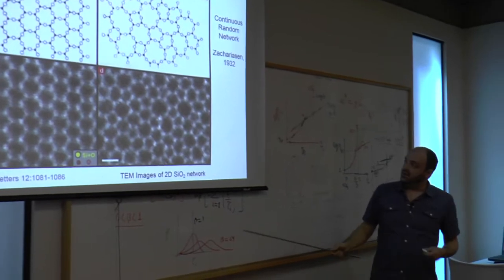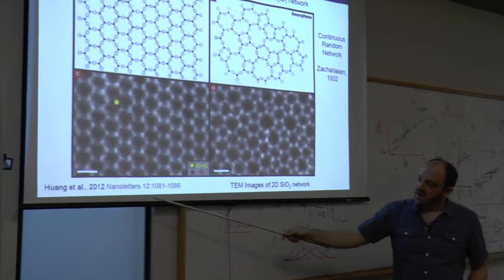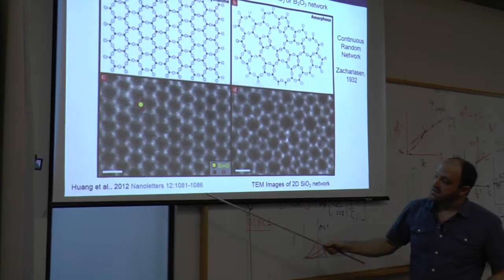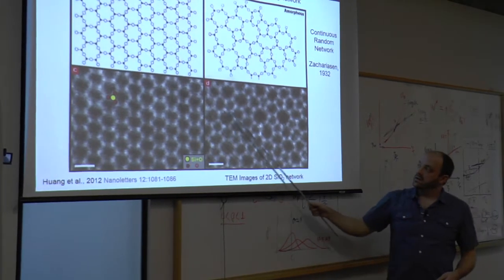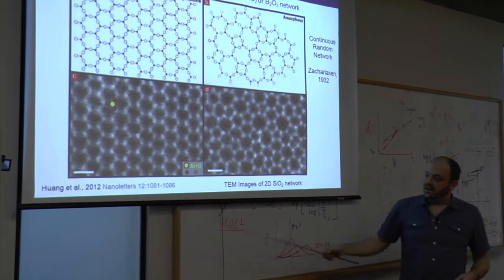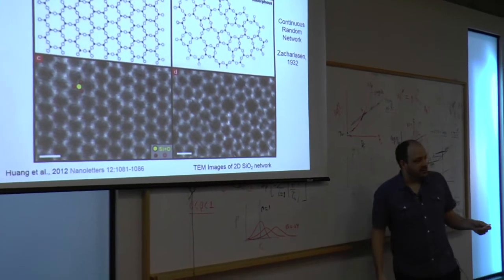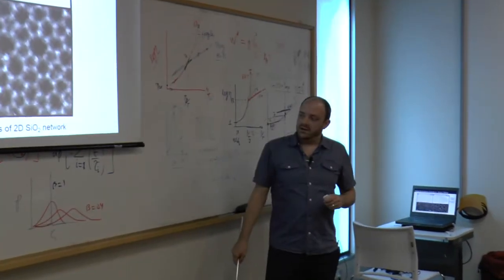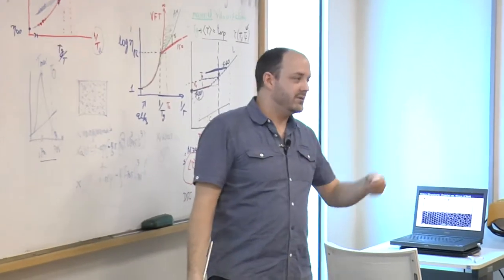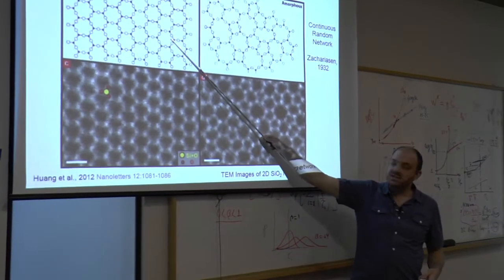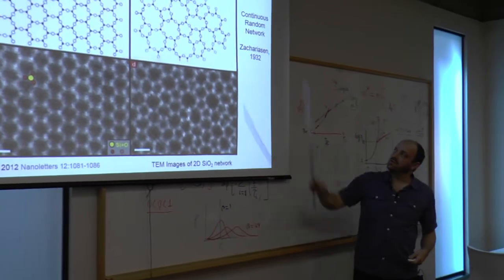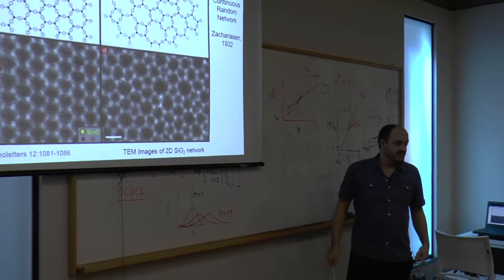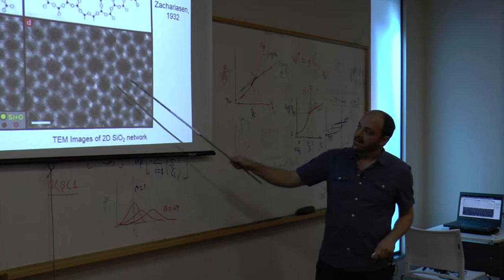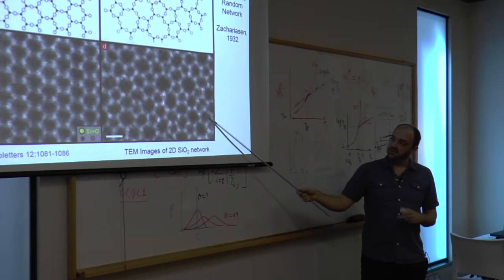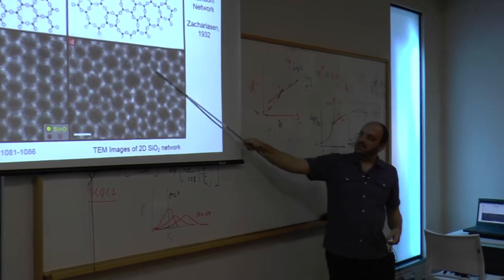Not much changed about this model for a very long time, but one of the interesting developments was that back in 2012, Huang et al. used a TEM to actually image the crystalline and non-crystalline parts of a material they were working on. And this is a great example of luck. They were actually looking at bilayers of carbon on a surface, and they happened to sputter some silicon onto their carbon layers, and then, oh, they got beautiful images of really well-ordered material that looked almost identical to our crystalline model, and they got disordered areas that looked almost identical to the amorphous model. And they said, okay, Zachariasen, back in 32, he really knew what was going on. If you actually zoom out, and in this paper there's a nice big figure here, there's a couple problems with saying that this is the same as this.